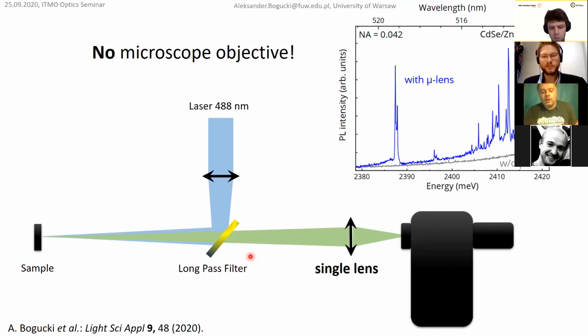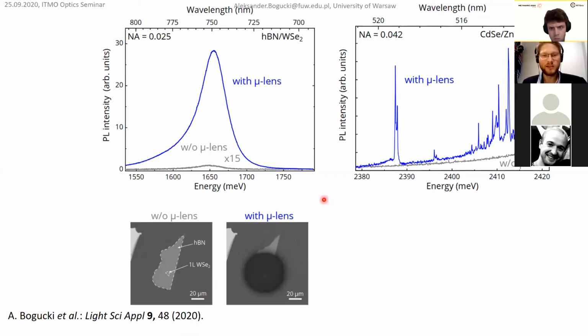So it's surprisingly good. As you can see here, the tungsten diselenide emits at 750 nanometers, so close to infrared, near infrared. And cadmium selenide quantum dots are at 520 nanometers. And we do not need to redesign the shape, because in that range the changes are so small. In fact, we can't see a measurable difference for such a big range, and we think it's big. It's because of the limited optical path in the microlens, because these microlenses are very small. So chromatic aberrations are not so important at this scale.